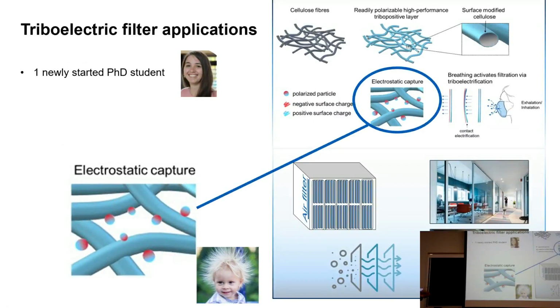What we want to do also is filtering, since that is another way of using this triboelectric effect. In fact, airborne particle filtering is used, but not with, I would say, any directed knowledge in the past. We have these kinds of effects, but we haven't understood that they are there and they could be important. So we want to direct this into more efficient filters by using our knowledge, both in cellulose but also in triboelectrics. One thing you can benefit from in these kinds of filters is that you can make them with much larger pores and still be effective. You use triboelectrics to capture particles on the material surface, which means you have a lower pressure drop and you can save energy in ventilation systems. But you can also think about face masks, of course, and easily breathable face masks as one thing.